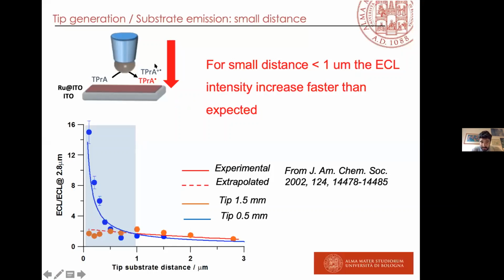But if we measure the emission as a function of the distance, like the same experiment that Bard did, the orange dot is with a bigger tip. When we go to a smaller tip, we have the blue curve, and we see that at large distance we have the same trend, but when we go closer to the ruthenium ITO electrode, we have an exponential increase. Amazing. We observe this exponential increase only with a smaller tip.